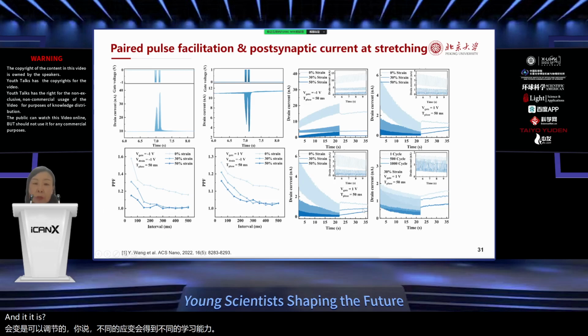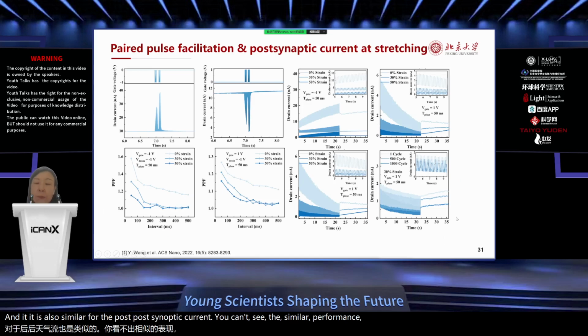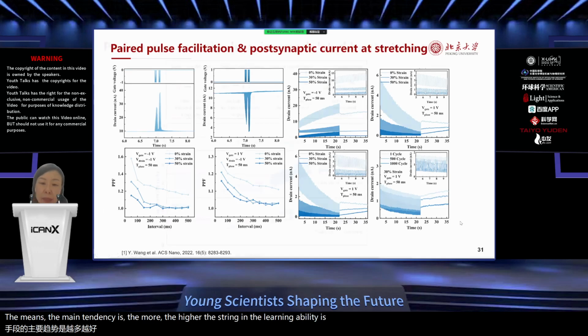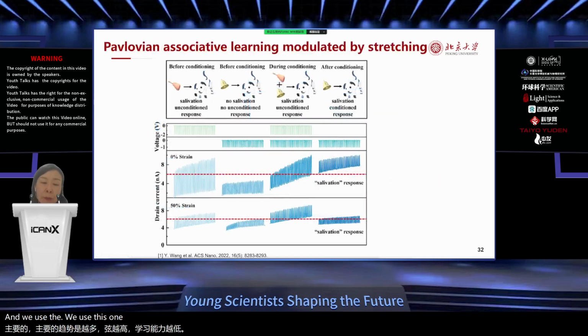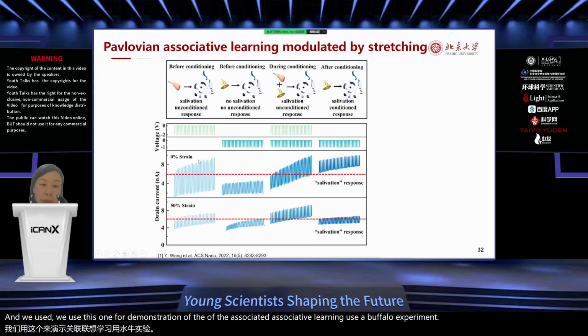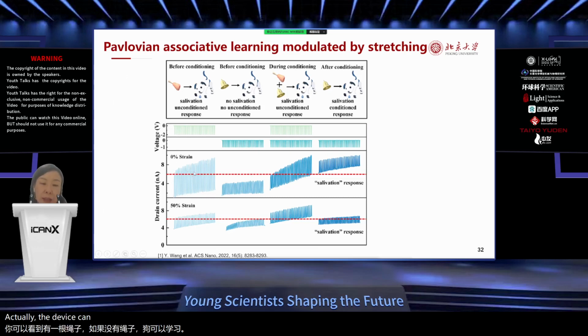It is also similar for the post-synaptic current. You can see the similar performance. The main tendency is the higher the strain, the more the learning ability decreases. And we use this one for demonstration of associative learning, using Pavlov's experiment. You can see with no strain, the dog can learn the device. It can have associative learning and can learn to release the salivation on the bell very easily. But if we apply 50% strain, the learning ability actually is decreased.